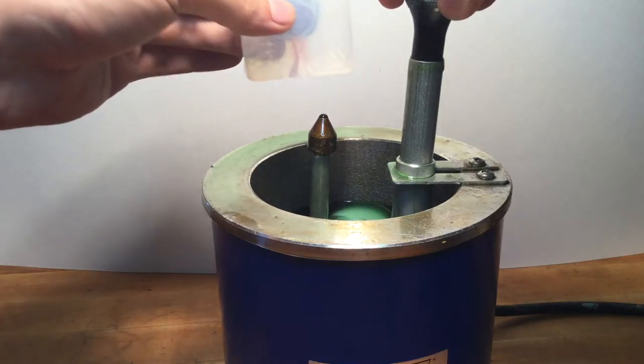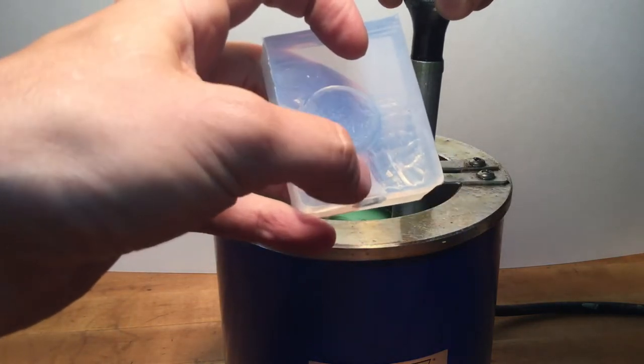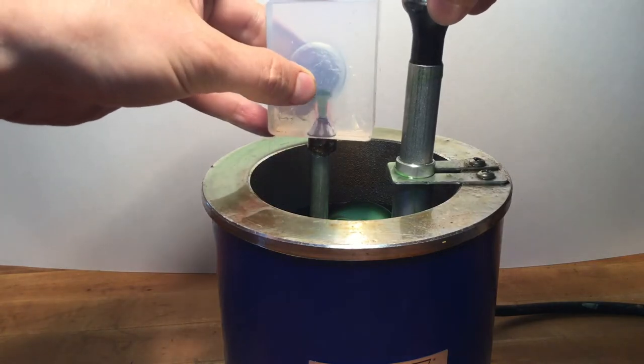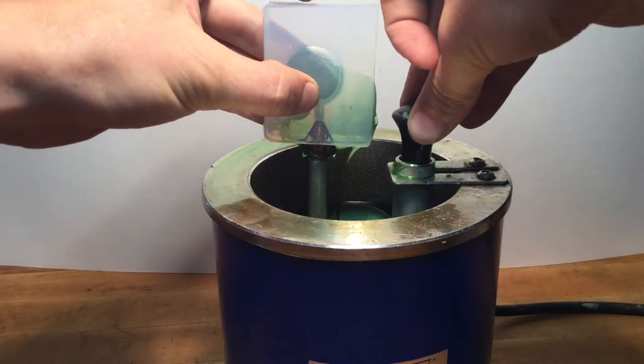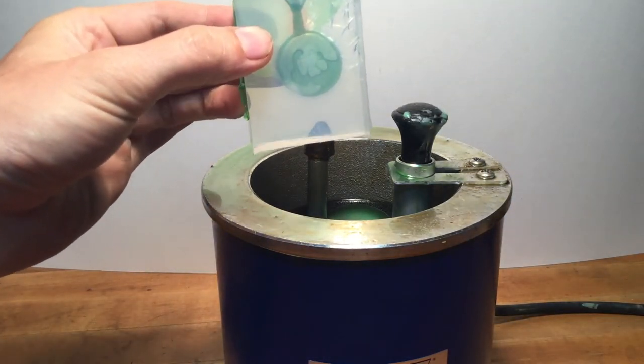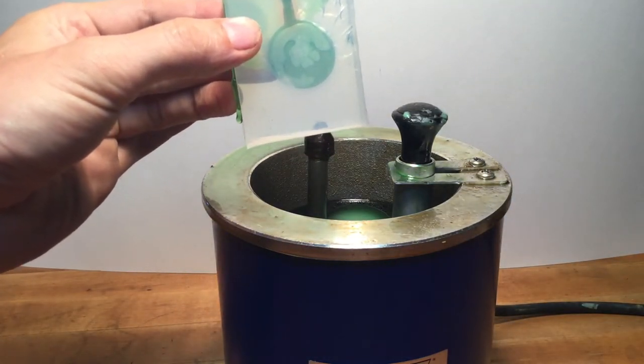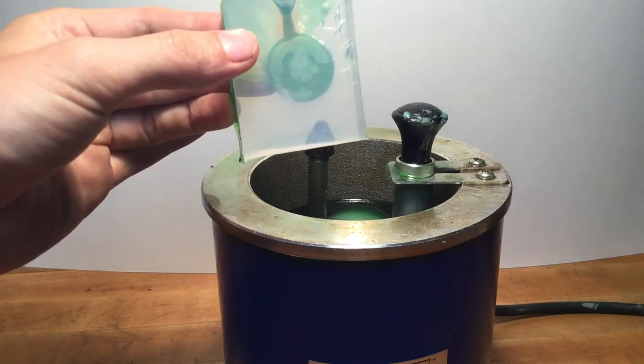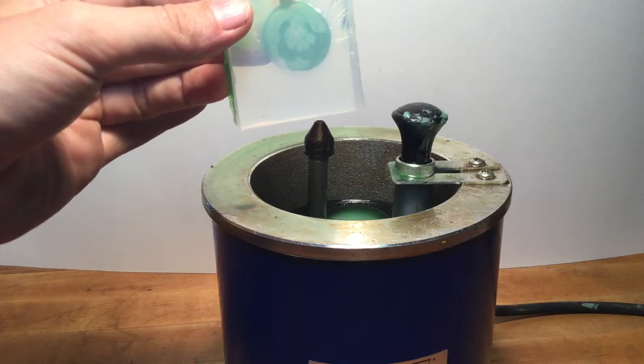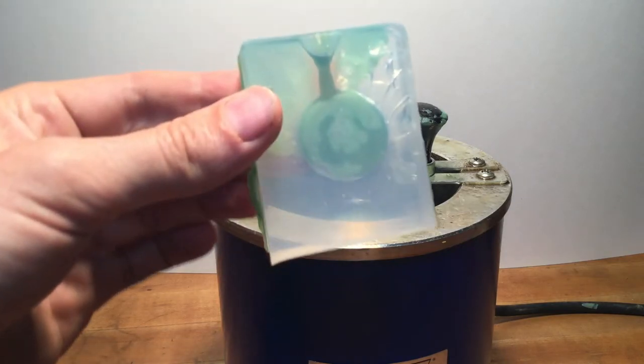So ultimately, you just need to make sure that the base of your rubber mold seats on this brass fitting, and then apply pressure to fill your mold completely. And then the tricky part is to invert it correctly. And if you don't get that flip step done on time, what you end up with is a mold that doesn't fill here.